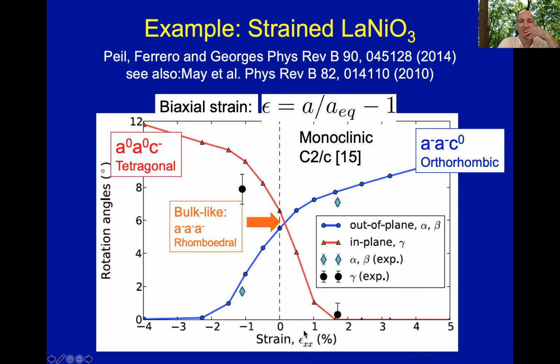What you see is a calculation in red of the in-plane rotations, meaning rotations along the c-axis, the gamma angle. And here, the rotations along the a and b axes, alpha and beta. You see that when you are compressive, you have a non-zero gamma and very small alpha and beta, while it's exactly the opposite on the tensile side.